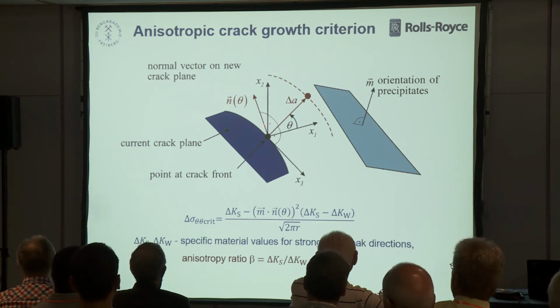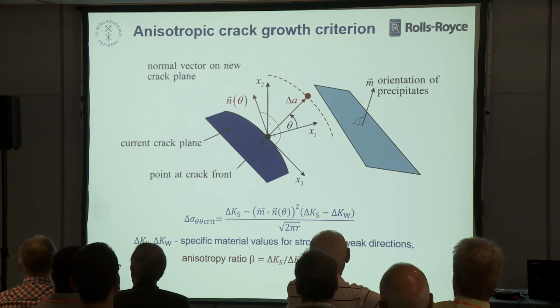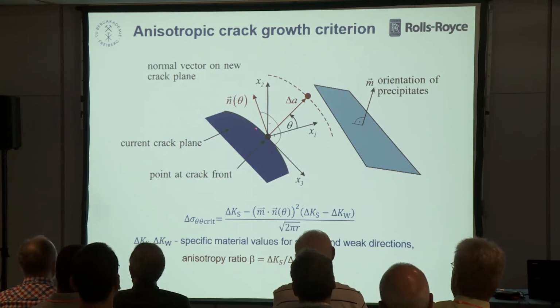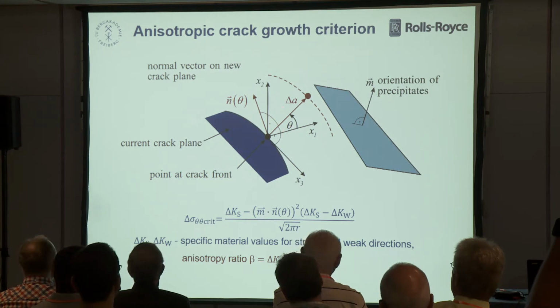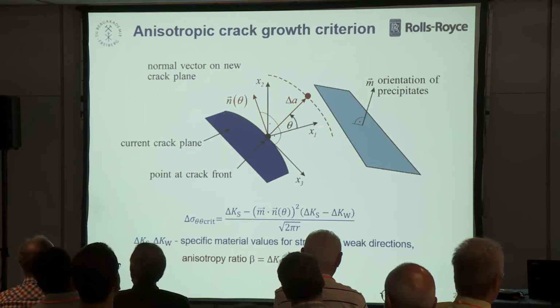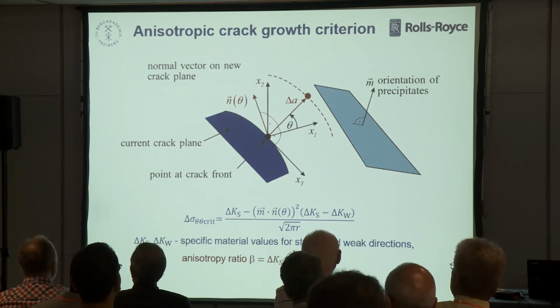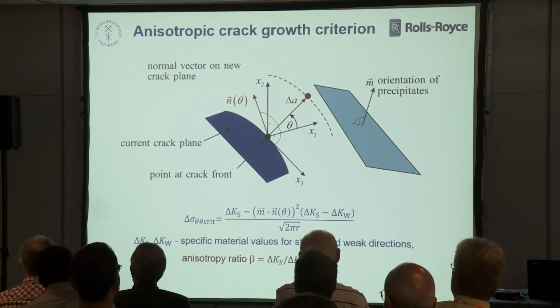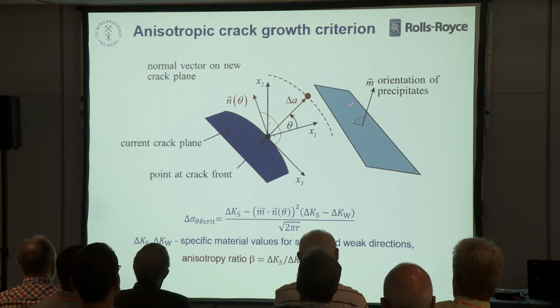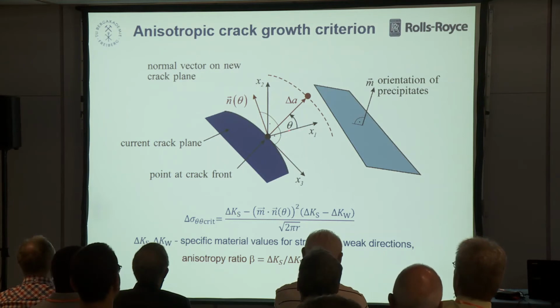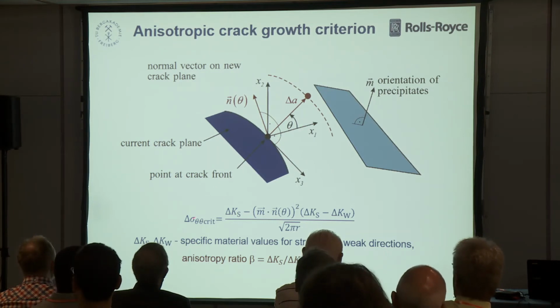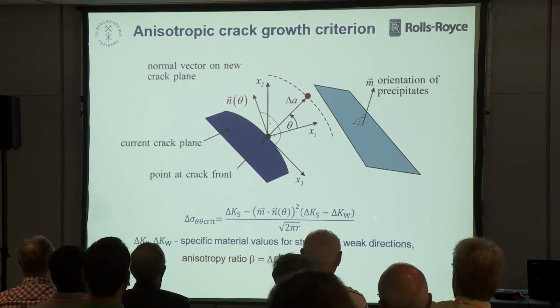And we have a coordinate system here, x1, x2, which moves with the crack front parallel. And we look for that direction n into which the crack will deflect. So the critical angle theta c. And our precipitates, they have any orientation. Yes, so they are defined by this normal vector m at this point. And for this resistance curve we introduce this formula.